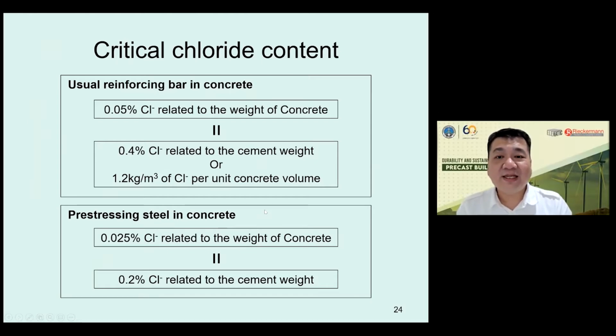And then one thing that we need to understand is that the chloride will cause degradation in the reinforcing bar when it reaches its critical chloride content. And then there's some standard. This is the Japanese standard saying that 0.4% of chloride relative to the cement weight can cause corrosion in the reinforcement. And this normally translates to maybe 20, 30, 40 years of exposure time. And for the pre-stressing steel in the concrete, the concentration is even lower to cause the corrosion.